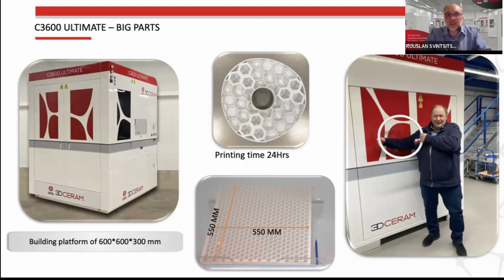So the build plate of this machine is big, 600 by 600 by 300, but it's not enough only to print the part. This machine is not easy to use and is not adapted to any application, and certain expertise in sintering is necessary, because when you do a very big part, you may have some distortion during the sintering process, and you have to pay attention to how to sinter this part, which would be the best way of sintering.